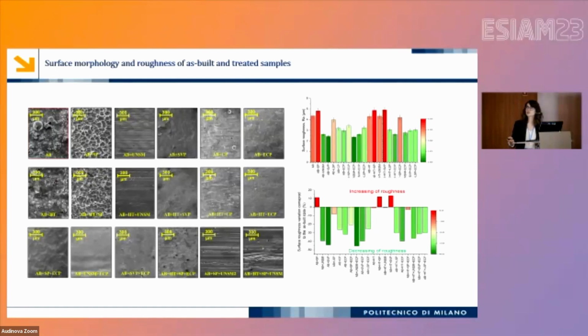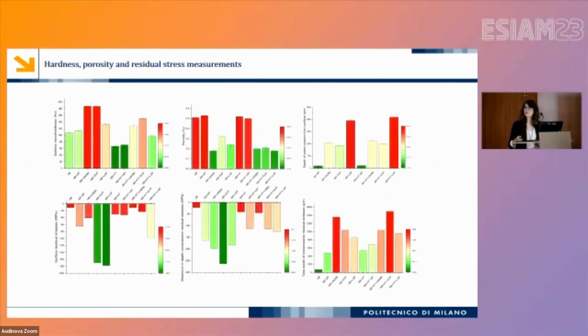We have done these treatments all on the as-built condition and also on the heat-treated samples. And here you can see the quantification of the roughness parameters. In most cases, we are reducing the surface roughness, and we are also slightly decreasing the scatter with respect to the as-built condition. We have characterized the samples also in terms of micro-hardness, porosity, and residual stresses.